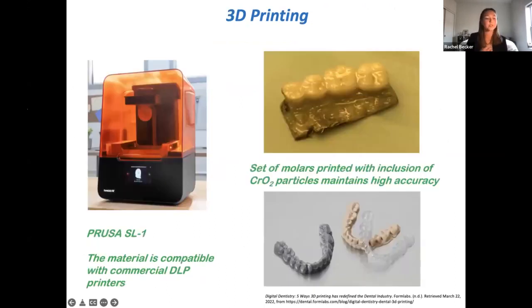So now looking more into the actual 3D printing of these materials, we see that our material system is compatible with most commercial DLP printers, such as the Prusa SL1. The set of molars printed on the top right was printed accurately, including the chromium oxide nanoparticles that I mentioned earlier. And these particles give us the control of light absorption through the sample while printing, as well as enable the induction heating process, which I'm going to talk about more on the next slide.